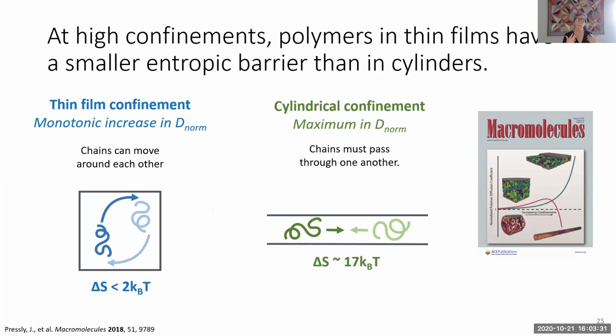So at high confinements, polymers in thin films have a much smaller entropic barrier than in the cylinders. And so even when it's very highly confined, they can kind of do-si-do around one another in the thin film, right? Because they have two dimensions of motion. But in the cylinders, it's really one-dimensional, and it's a huge entropic penalty for the chains to pass one another and for center of mass diffusion to happen. Okay, so I think we have finished our first topic, polymer diffusion in confined geometries.